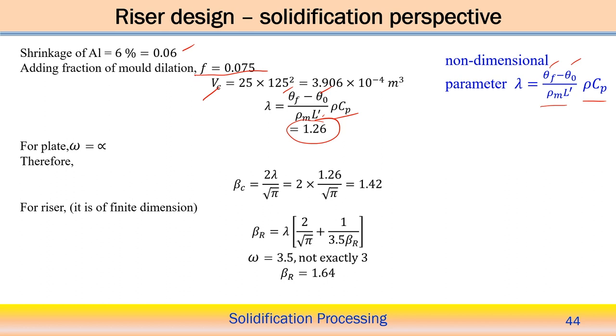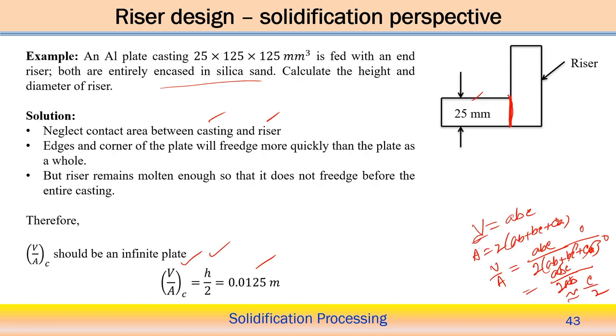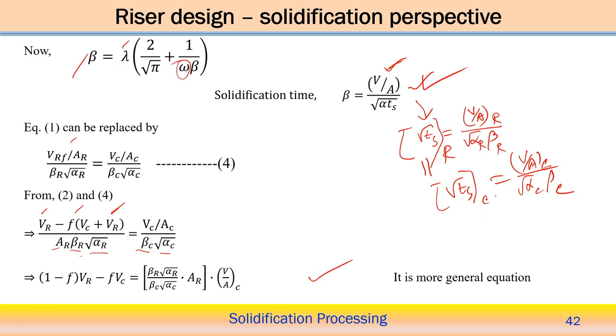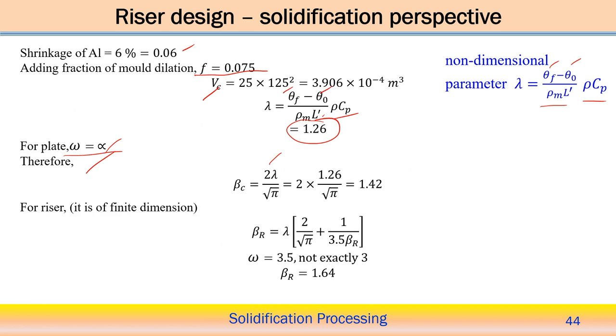So, once we calculate the value of lambda, then for an infinite plate, in this case omega equals infinity. So, therefore, we can consider the beta value equal to twice lambda by root pi. We are using here omega tends to infinity for the flat plate, so 1 by omega tends to 0, and this term will be 0. So, beta equal to lambda into twice by root pi. Lambda we have already calculated with the other parameters; L and rho m are associated with the molten metal, and rho cp is associated with the mold material. So, putting all these values, we can get this value.